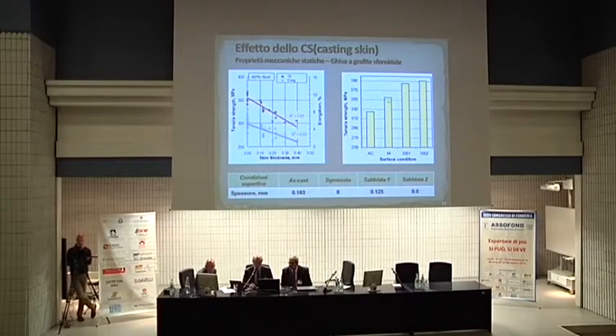And here it's an effect of the surface condition, because we have means to deal with the surface condition. For example, this is the properties if I take the sample without machining, as cast, and if you machine the sample, then the strength goes up significantly. And then if you shot blast the sample without machining, so this is as cast and then shot blast, you can see a much higher increase in strength. And this is when you shot blast it for a longer time. So I think this was 2 minutes and this was 5 minutes. And the effect of shot blasting is basically to decrease the casting skin thickness from 0.183 millimeters to 0.125, and then after 5 minutes completely remove it.